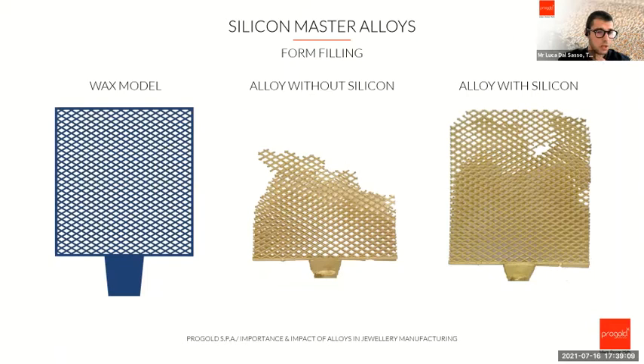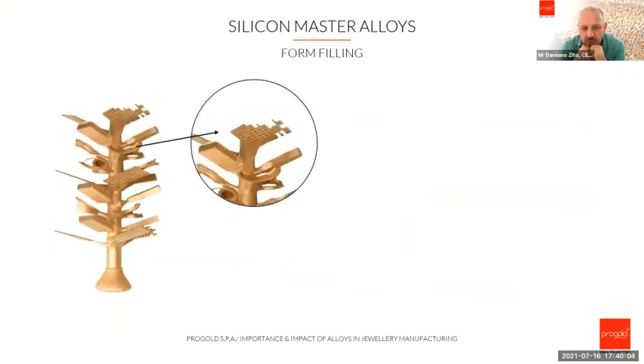We prepared this wax model appropriately to test the form filling, but with the silicon added to the master alloy, we were able to fill almost everything in the model. Let me say also, of course, there is something connected to the wider melting range of the alloy due to the silicon content. But another thing is that the silicon somehow is modifying the ability of the alloy to lose less energy every single second. So it loses not 1 degree per second, but 0.8 degrees per second. So it has more time to fill the mold. And this is also the next reason why silicon helps very much on this matter.